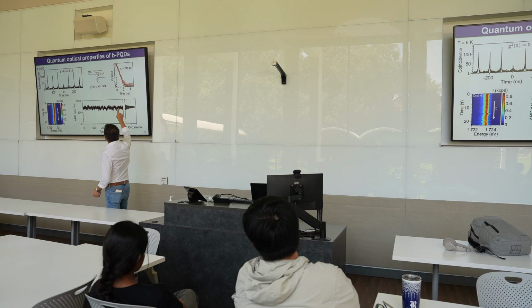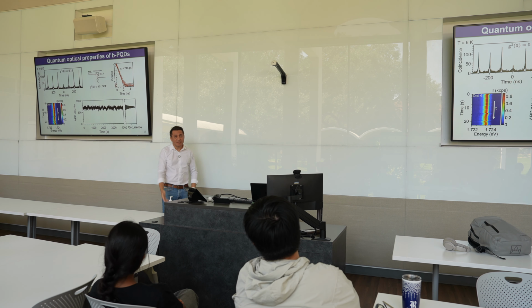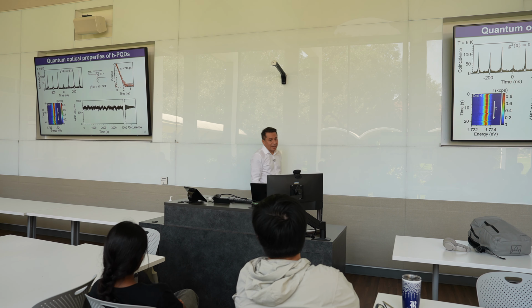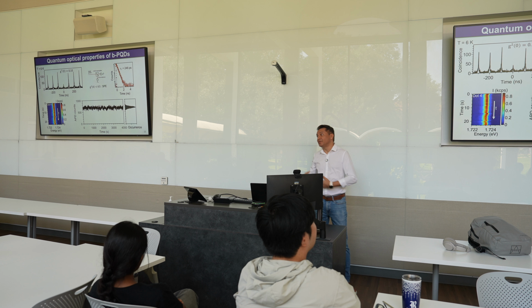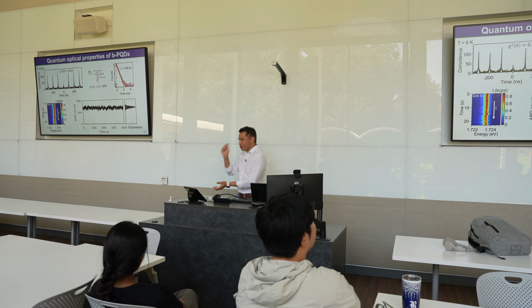And they have really short lifetimes. You have a 246 picosecond lifetime, and this is the radiative lifetime of the exciton. Obviously, the excitons are short-lived. They want to recombine. They don't want to stay like this. They're not free carriers. They're not screened. So they want to do that.